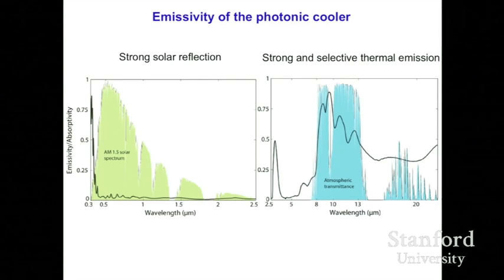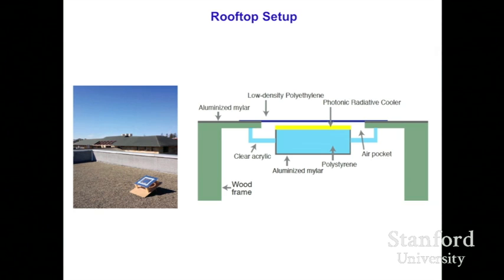So under white light, this is a fairly good mirror, so it reflects all the sunlight. And if you look at the measured spectrum, it has very low emissivity throughout the solar spectrum, and yet has an emissivity peak in the 8 to 13 micron window. So we then bring this on top of the Packard Electrical Engineering building. So this is the picture of the setup. We tilt the sample to the south, towards the sun, because we would like to be able to demonstrate this in the worst possible scenario, so as to get as much sunlight as possible.